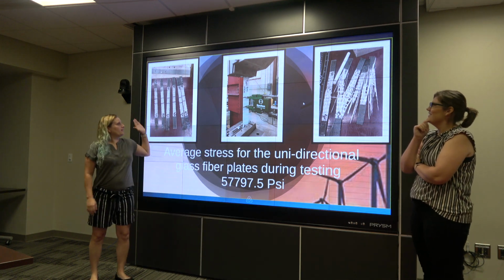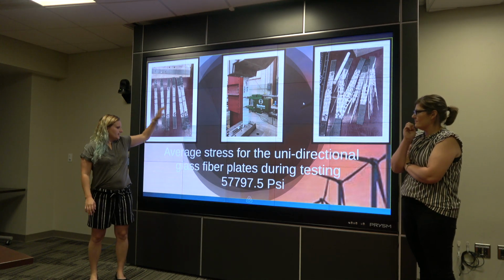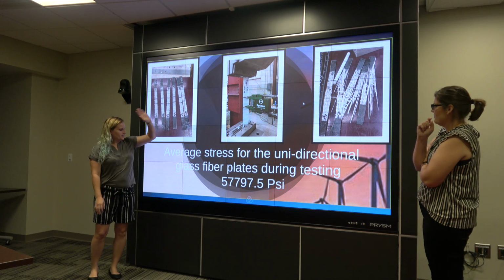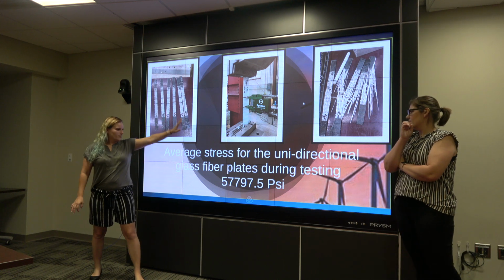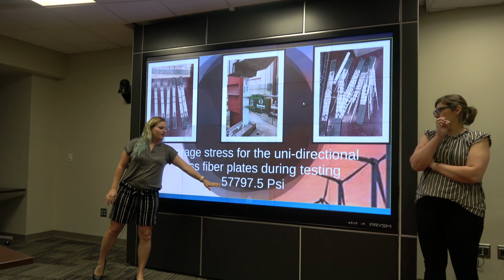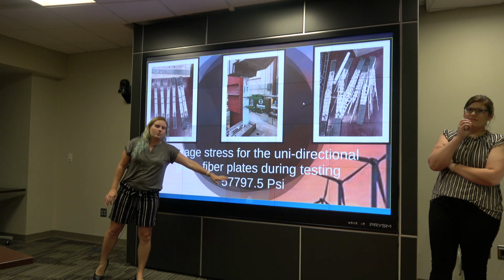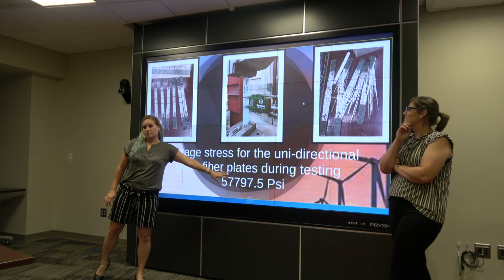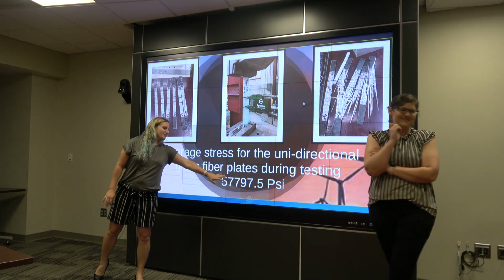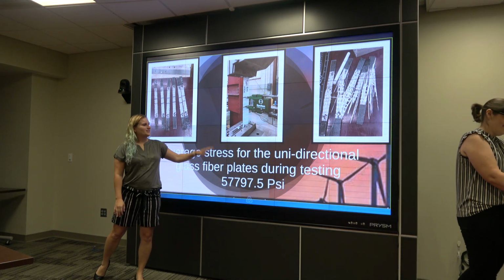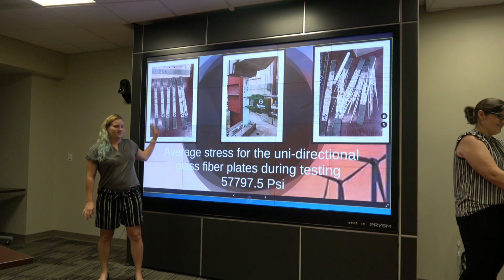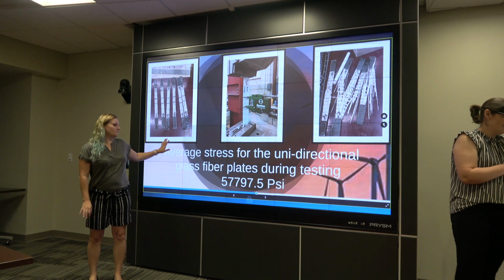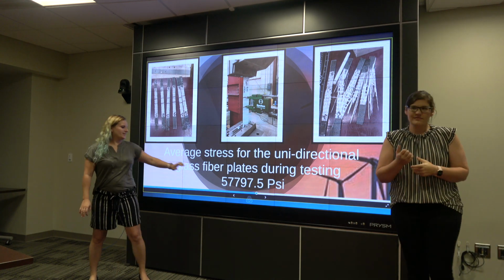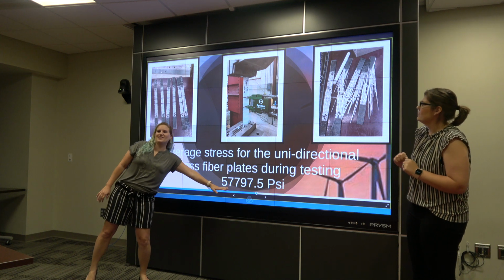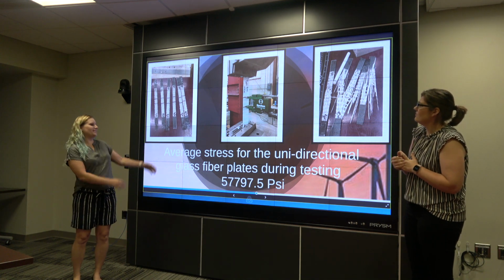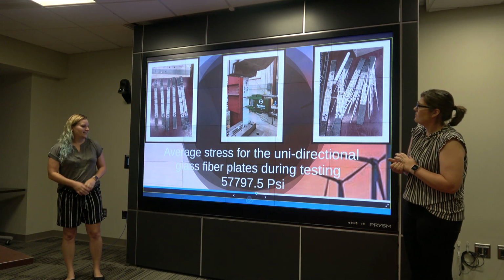So what we found out from this testing is that the average stress for this unidirectional glass fiber plate was actually 57,797.5 pounds per square inch. So what we found out is that not only could it withstand the highest wind speed in Oklahoma, but it is actually way higher than that. So we determined that yes, it definitely does have that strength.